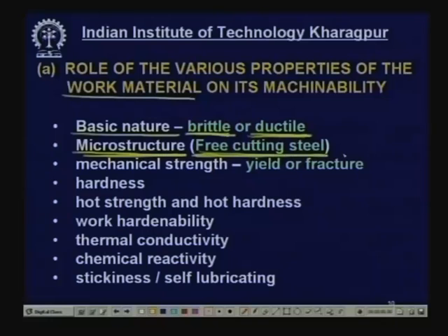So, it improves. Not only that, the morphology of the manganese sulphide inclusions plays a role in solid lubricity, and the morphology is favorably changed by the addition of some material like tellurium. Tellurium is the best possible material to control the morphology of manganese sulphide, by adding sulfur to react with the manganese present in steel. So, these are very easy to machine.